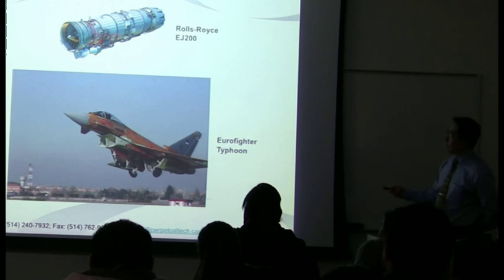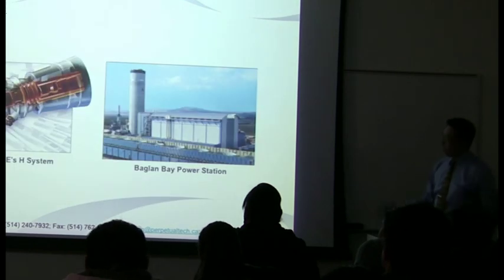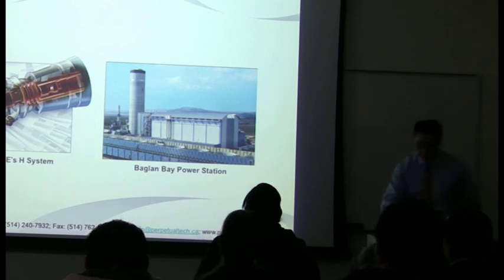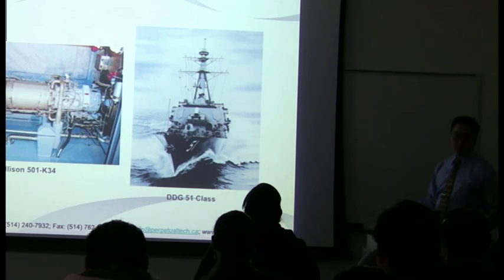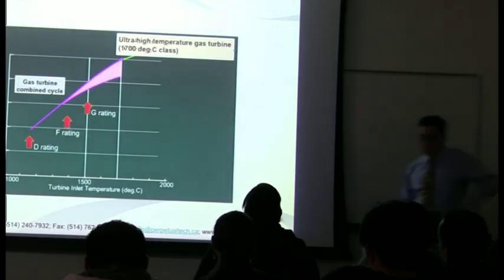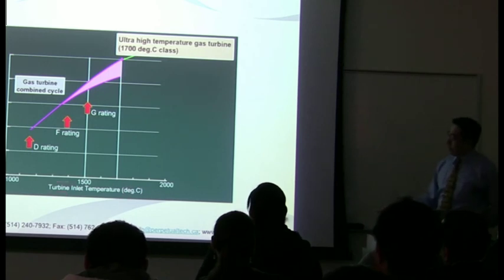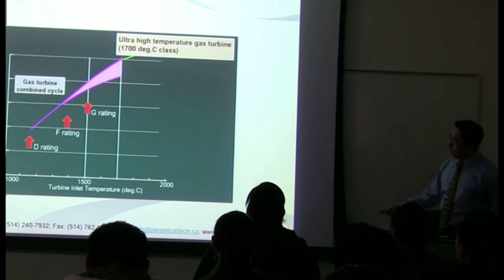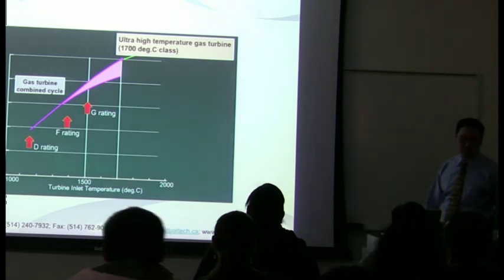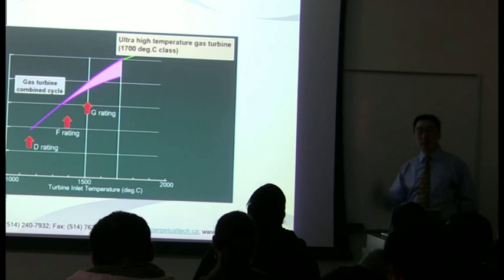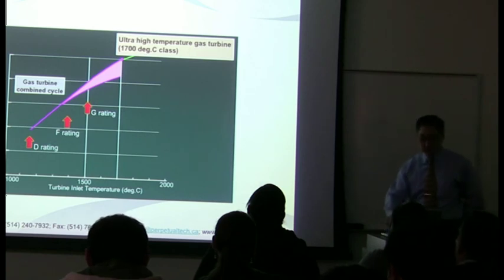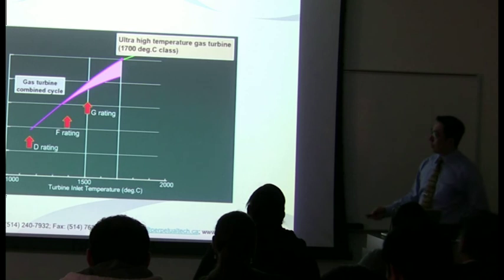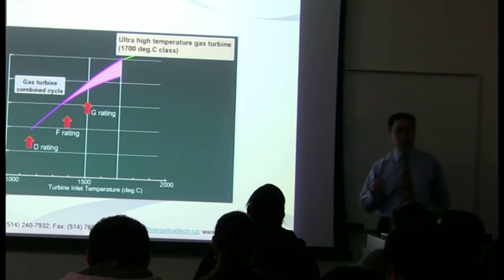Now, gas turbine engines are used for jets. They're used for land-based energy, electric energy, and they're used on ships, on electric boats. Now, there's a strong push to increase the turbine inlet temperature. And you can see why. When you look at the thermal efficiency of these engines, they increase dramatically the more you can ramp up this temperature. The only issue, once again, as a material scientist, is how can you produce materials that can withstand higher temperatures for long periods of time? And that's a real problem. And in addition to higher thermal efficiency, when you can increase the temperature, you also decrease the pollutants from these engines, which is obviously an important factor also.